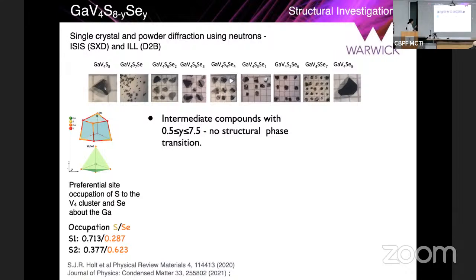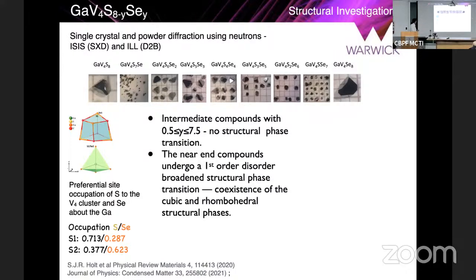So what we looked at was the structural transition, because it is very key to the magnetic transition as well. There's a strong link between the structural properties and the magnetic properties in this material. Remember, we need a non-centrosymmetric space group where you have the Dzyaloshinskii-Moriya interaction to give rise to the antisymmetric spin-orbit coupling, and therefore result in the formation of the skyrmions. So the first thing to look for is a structural transition in all of these intermediate compounds. And we did not find a structural transition in any of these materials, except those very, very close to the end compounds. So what we then did was to look at compositions very close to the end materials.